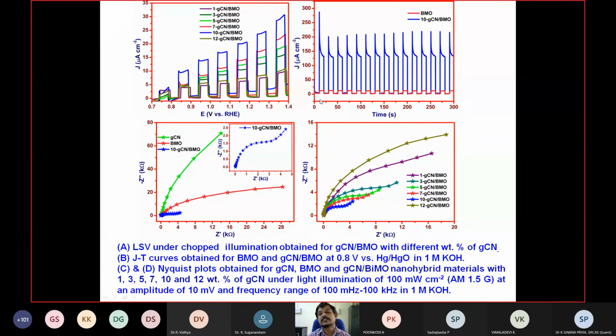Likewise, you just look at this system. We optimized the applied bias potential, then fixed the constant potential and performed the experiment through chronoamperometry. Here, when there is no light, there is no current. Once we switch on the light, the current goes up, and when it is switched off it comes down. Again, we chop the illumination, and it goes up and comes down like that. We did this for several cycles, and the photocurrent is highly stable. That means the prepared material is highly stable.